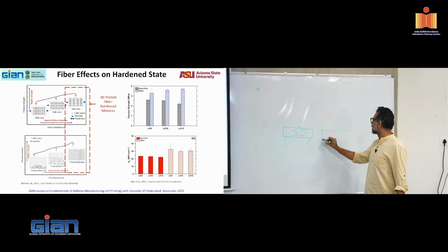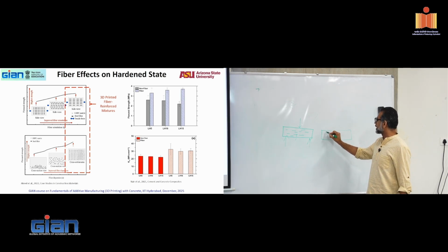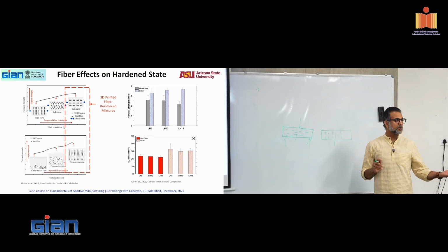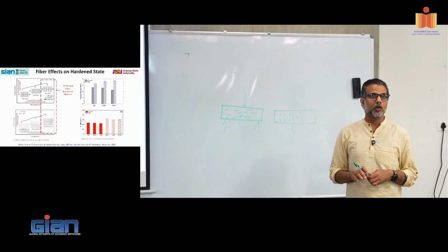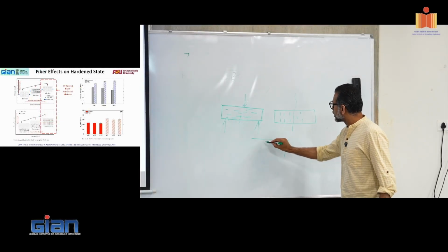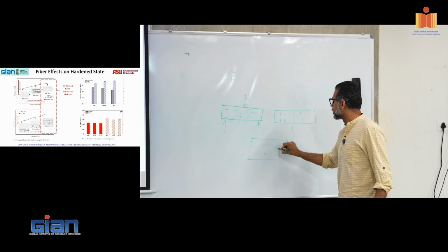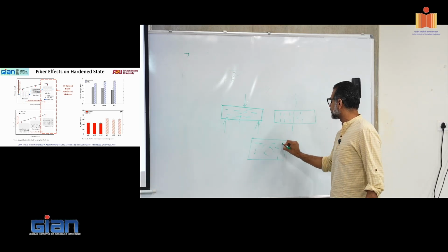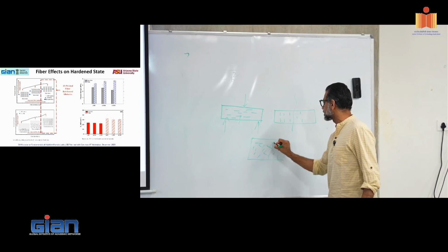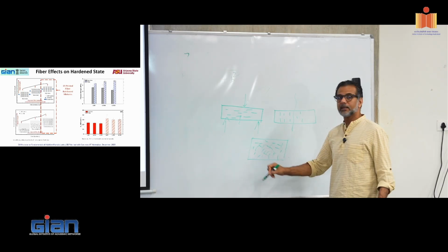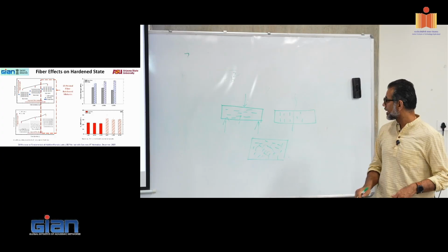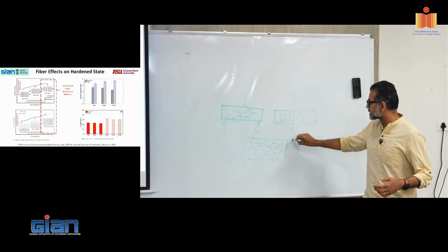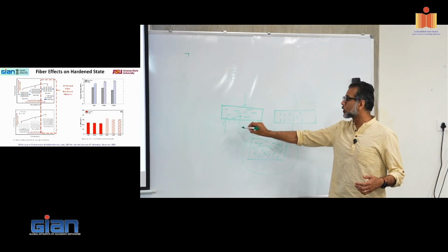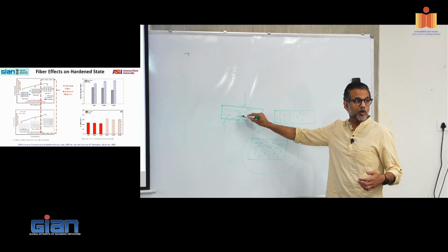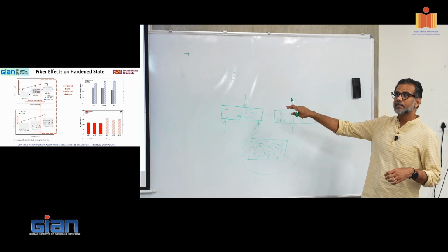Whereas if you print it in such a way that fibers are aligned like this, a crack can go right here. You might not see any influence of fibers at all. If you have normal casting of concrete, you expect the fibers to be in all different orientations, all different directions possible, which means statistically there is a chance of finding a fiber everywhere, and that's why the properties are increased. In this case, the properties are much more increased because you're absolutely certain to find a fiber on the path if you have fibers aligned in that direction.